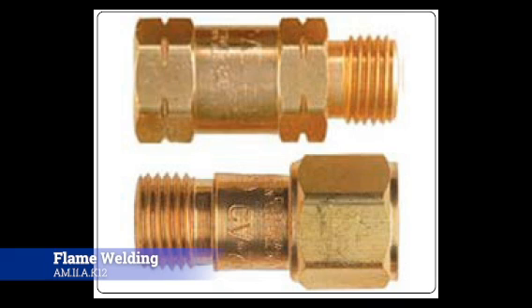Okay, next will come the check valve. The check valve stops the reverse flow of the gas, and can be either installed between the regulator and the hose, or the hose and the torch. In our particular situation, we're going to say it's installed on the torch end. Excessive overheating of cutting, welding, and heating tips can cause flashback conditions, and a flashback can be caused when the tip is overheated and the gas ignites before passing out of the tip. So effectively, the torch gets super hot, and then it starts burning inside of the torch instead of outside of the torch. The flame is then burning internally rather than on the outside of the tip, and is usually identified as a shrill hissing or squealing noise.